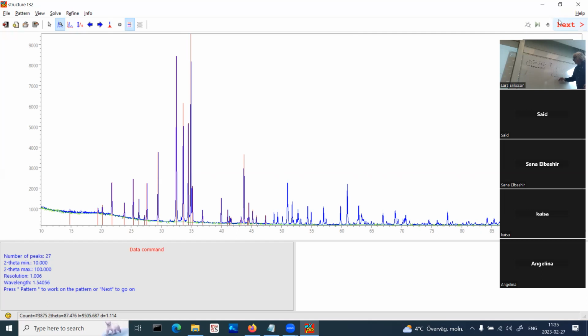But say that we only use these, then this is actually more or less a straight function, and even with erroneous cell parameters, it would find the cell parameters with a very small error window. So the difference from a straight line is quite small.